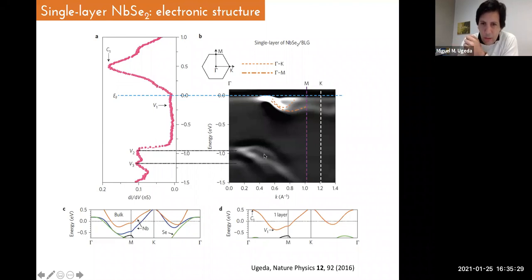So at lower energies, we already have the selenium-based bands that have an effect in the STS curve. This is an STS spectrum. So these two peaks correspond to the selenium-based bands. The effect of these pockets on the electronic structure, at least in the STS, is not big because these pockets are really far from the gamma point. And the most prominent feature is this peak, which is an empty state, and that we attribute to this band that is basically crossing the gamma point here at around half a volt.